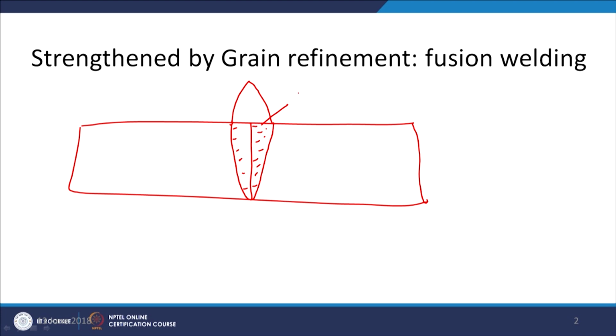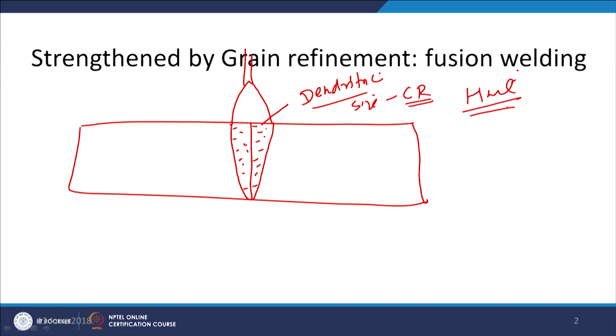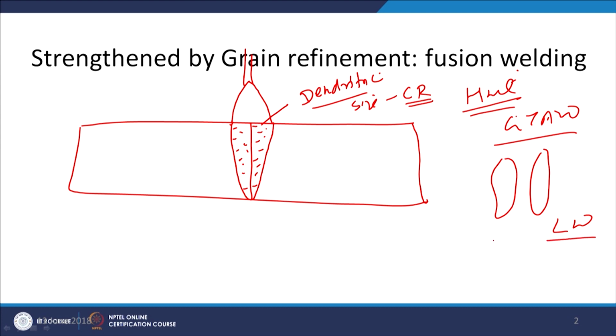this zone will not have any effect of the prior grain refinement, because the grain structure here will be completely dendritic, and the size of the grain will be governed by the cooling rate experienced by the weld metal during the welding, which in turn will depend upon the heat input which is being given. If the heat input is high, like in the case of the GTAW process, then the grains will be coarse, and if it is the laser welding process where heat input is very less, the grains will be extremely fine and they will be well distributed.